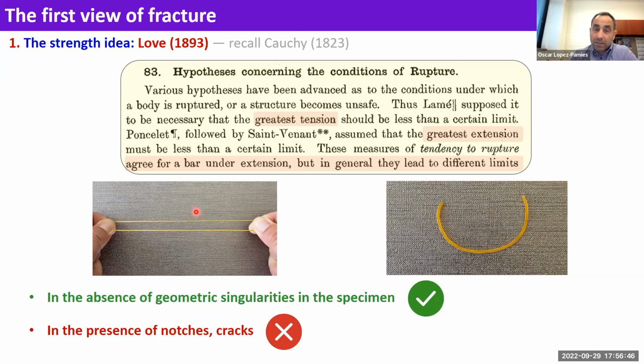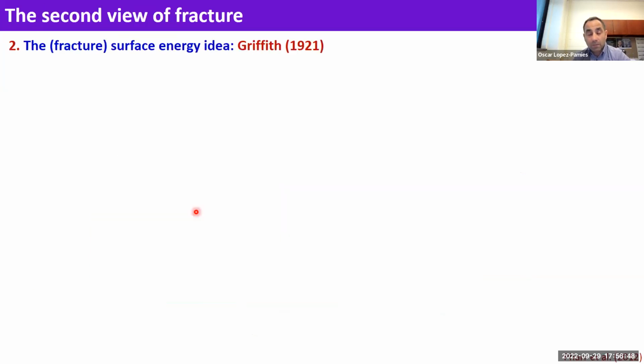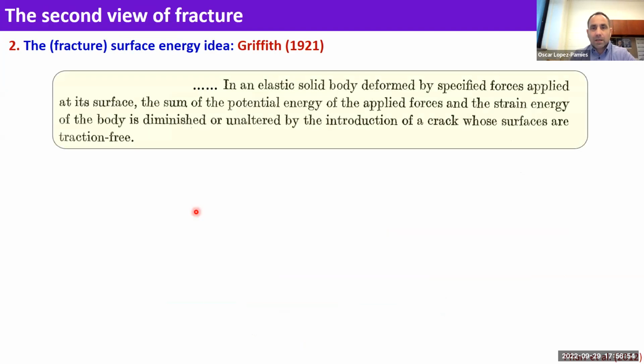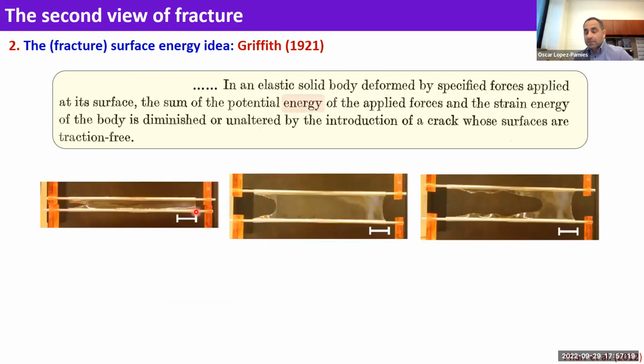So this was in the 1800s. Then along came Griffith, 1921, several decades later. And he said, actually, strength is not what matters. What matters is a competition of energies. If you take a piece of material, the material may fracture or not, depending on a competition between the energy of deformation and the energy associated with the creation of surface. And this works great, but only when you have a crack in the specimen.